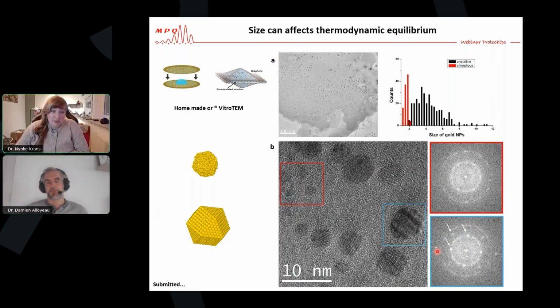I like that you were able to prove that as well, because I guess it's really hard to prove if they're actually in or out of focus, if they're in or out of crystal plane, or if you have enough resolution. The resolution is good enough for sure. Orientation may have been a problem, but to me it's clear that with all those nanoparticles that are amorphous, we have tons of data of them, how could they all be out of Bragg orientation? It's extremely unlikely. So to me we clearly have a phase transition.